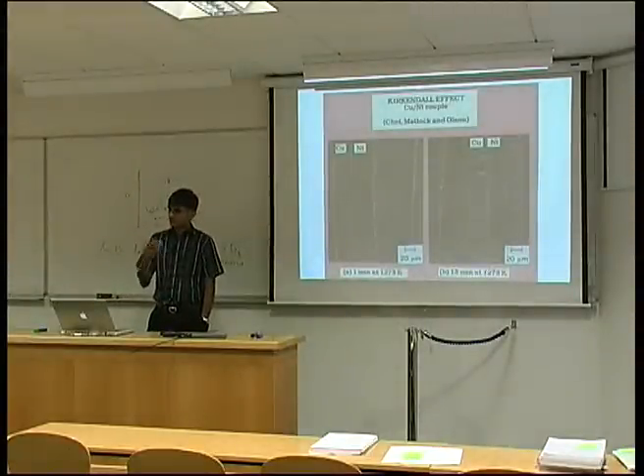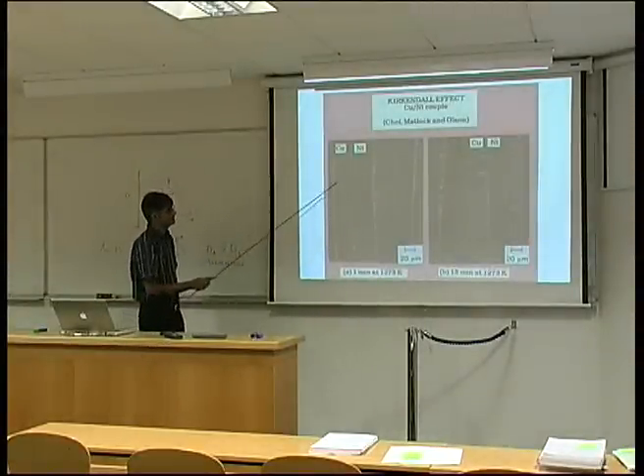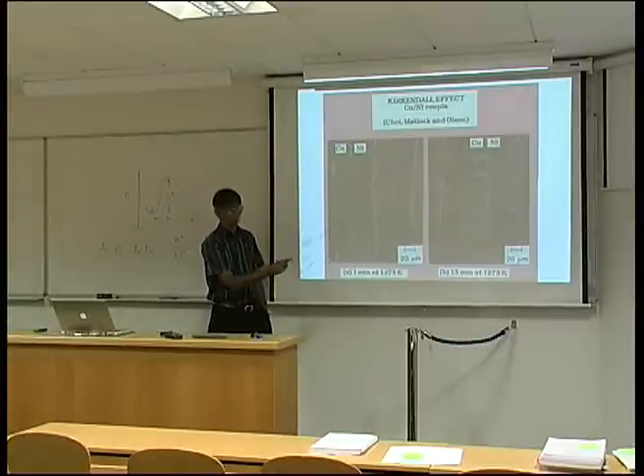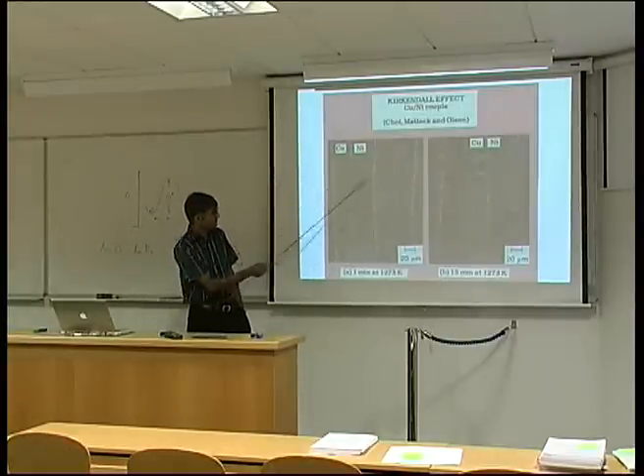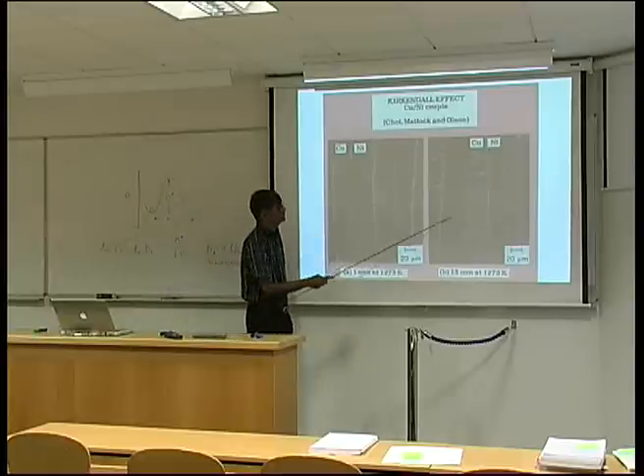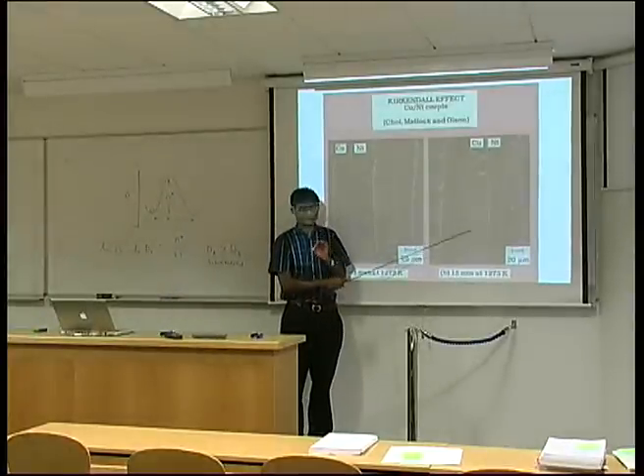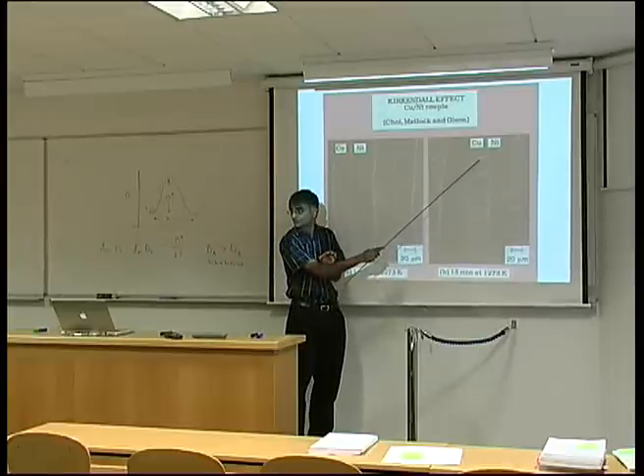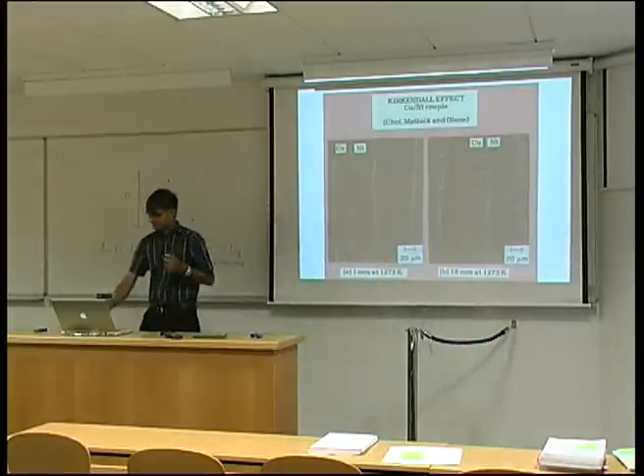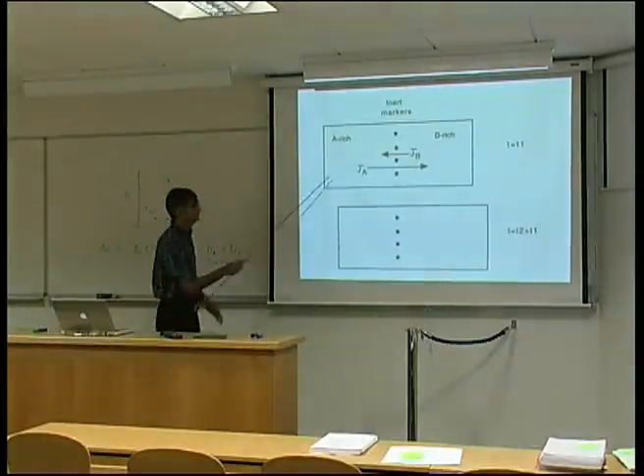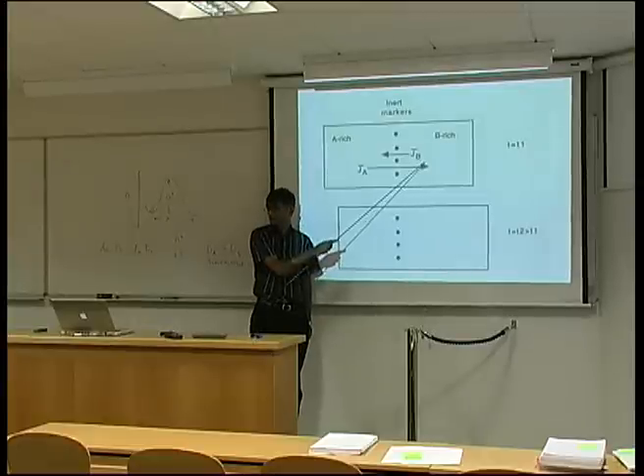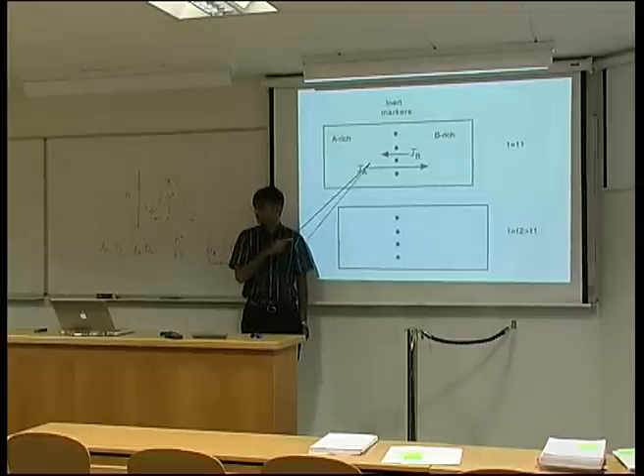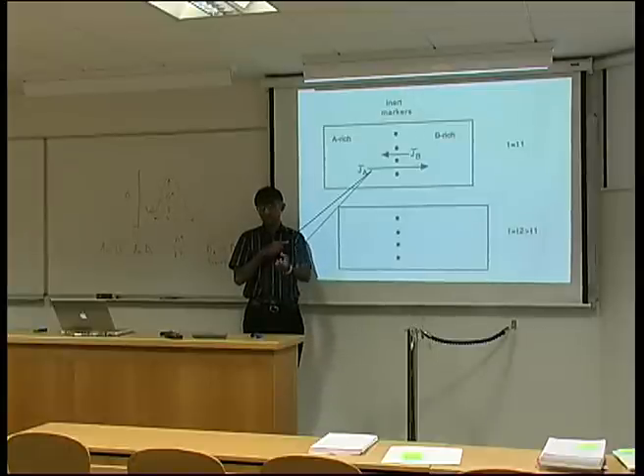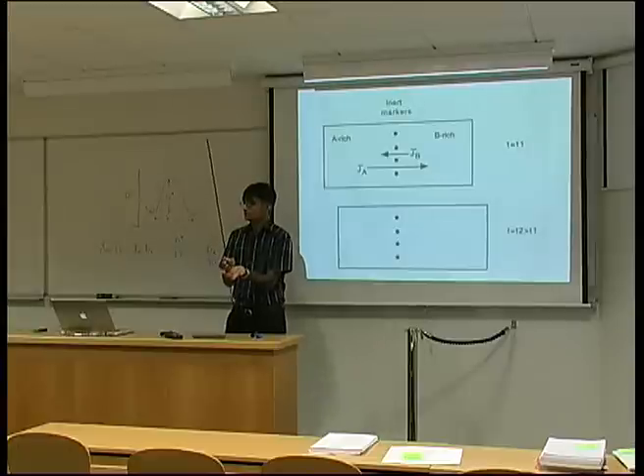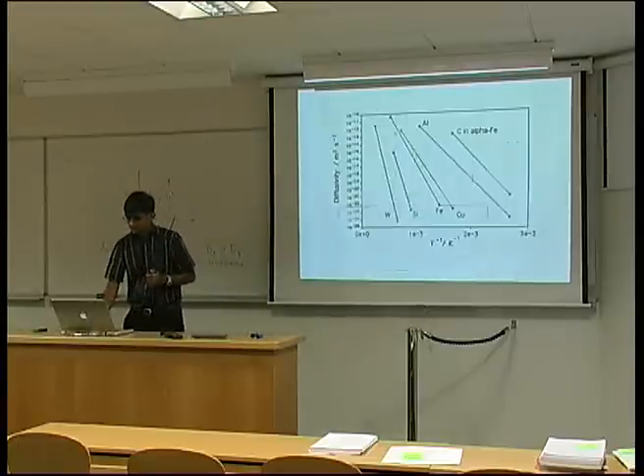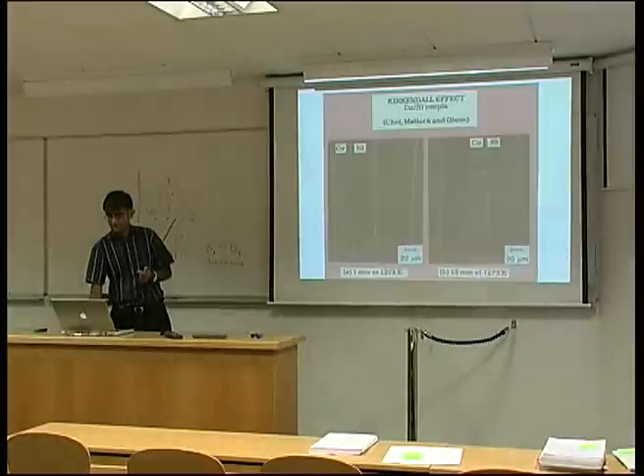You can actually see this when you make diffusion couples. So here, for example, layers of copper, nickel, copper, nickel, copper, nickel. And this is before diffusion. You allow diffusion and you end up with porosity. That means large holes. You can see large holes here inside the copper. Now the reason why you end up with large holes is that if I've got matter moving in this direction, then I've got vacancies moving in the opposite direction, and they will tend to condense here. Vacancies will tend to cluster and form porosity holes. And that's what you see in this slide.